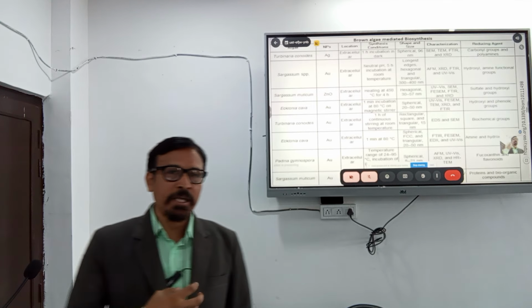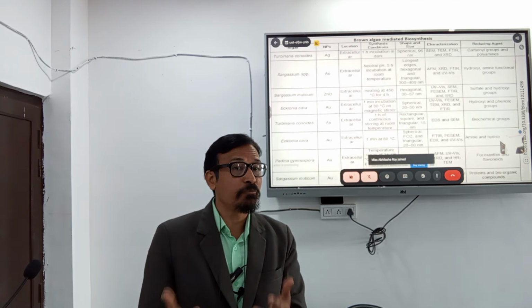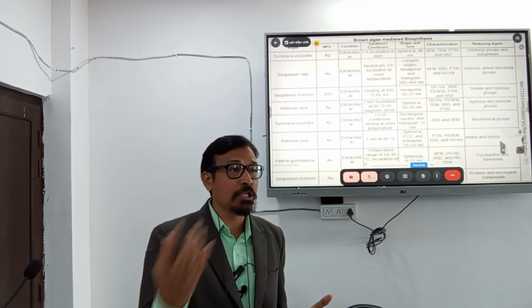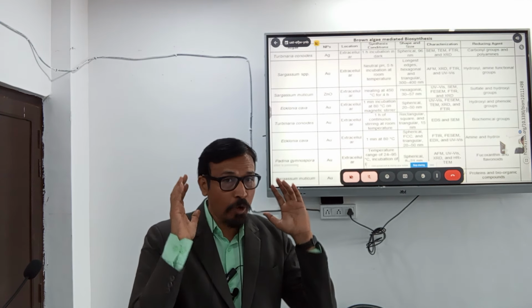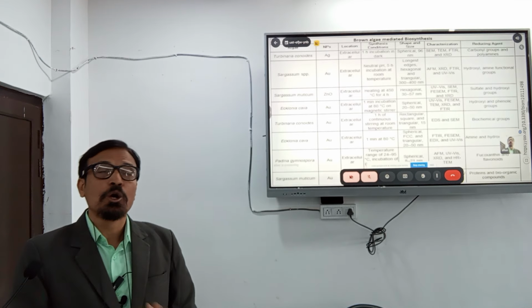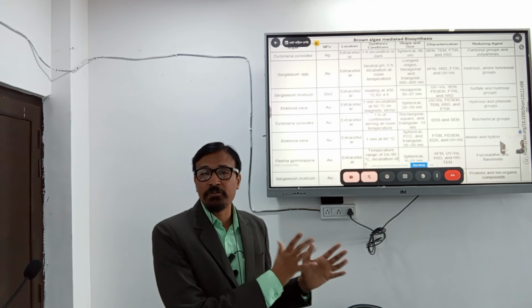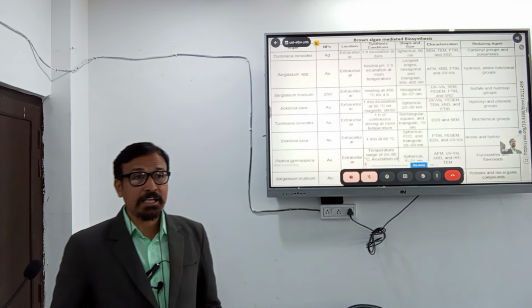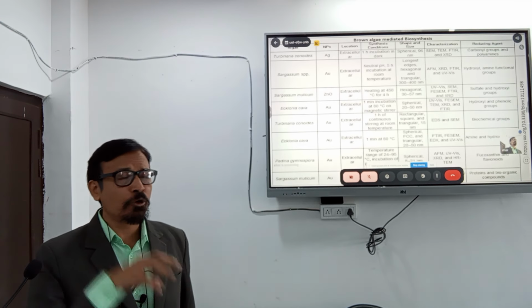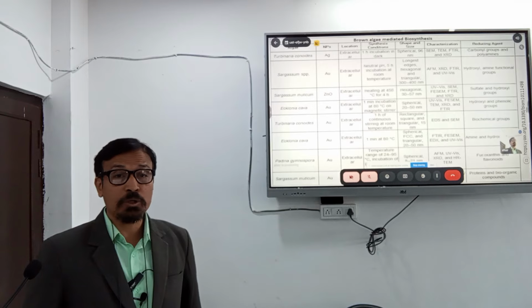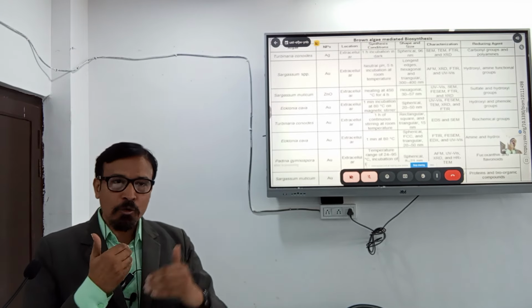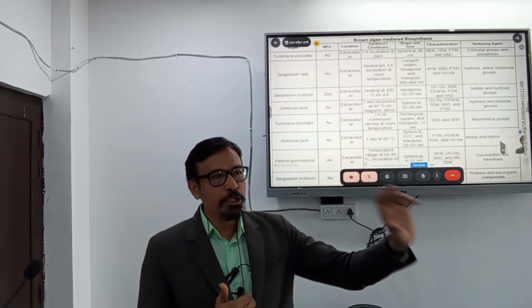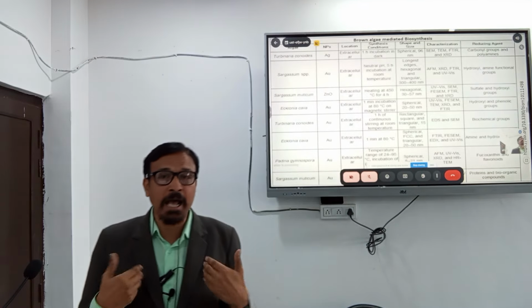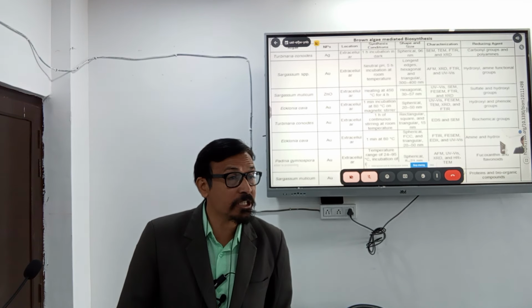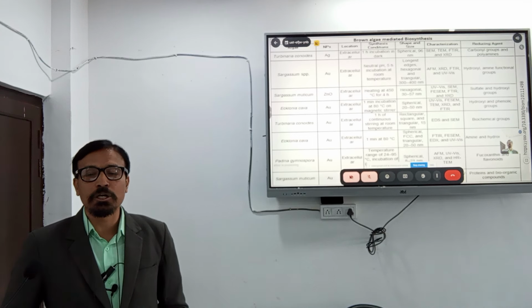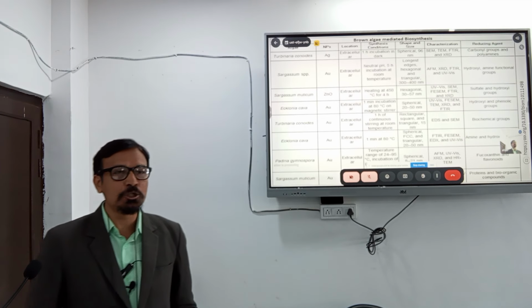And the characterization: once we synthesize those nanoparticles, we have to characterize them to see whether they are useful or not. If the size of those nanoparticles is too large, the agglomeration rate is too high, so there is no use of those nanoparticles. That's why we have to characterize them with many sophisticated techniques, like scanning electron microscope, transmission electron microscope, Fourier transform infrared, and XRD. And what is the thing inside this algae which can reduce the ionic species so we can have the metallic form of those nanoparticles? These are the reducing agents, and in Turbinaria conoides they are carbonyl groups and polyamines which can reduce the ionic species.